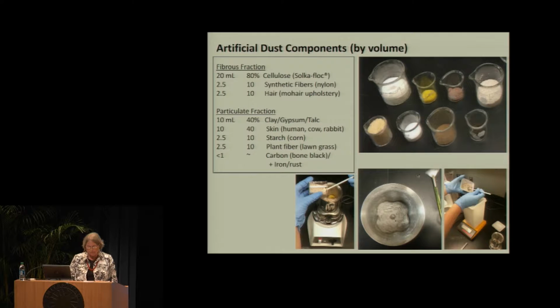So for distribution of my dust onto the samples, I looked at an ASTM standard for accelerated soiling of pile yarn floor coverings as something to consider. And I used a Tupperware saltine cracker container as a tumbler. For each sample, I used 5 grams of artificial dust that was measured by weight in the tumbler, and the samples were tumbled for 2 minutes, a minute forward and a minute backwards.